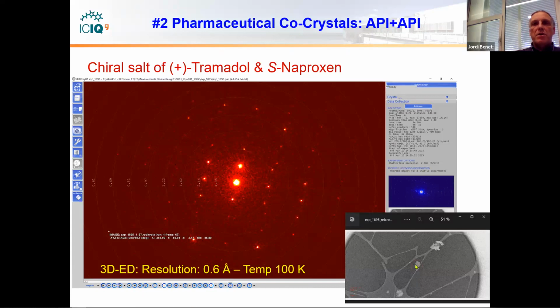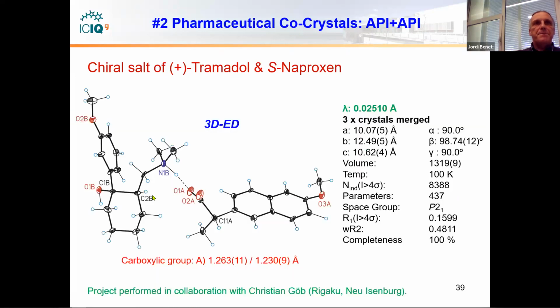Here you can see one of the crystals we measured, and also the diffraction pattern. In this case, after merging 3 crystals, we could get the same structure, of course, with a good parameter to reflection ratio. And we have an R value of 16%, which is, I think, quite good.